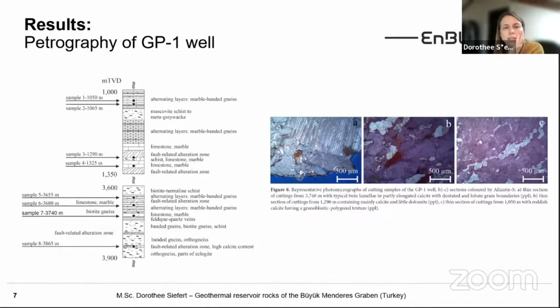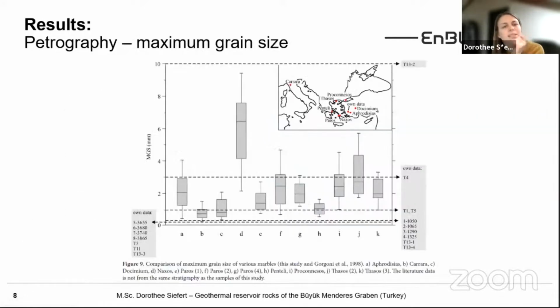And yeah, it contains a small amount, less than 5%, of quartz and mica. So about the maximum grain size we analyzed of the calcite and dolomite grains, they are in a quite small range, and one outlier is the Paleozoic outcrop sample T13-2. So here are our samples, and the box plots are the samples compared to various marbles in the region, but also in Carrara, for example. So the maximum grain size of the well samples appears to be small compared to the surface samples, but we can observe no systematic difference, and the cutting size is about 5 millimeters. So this may have influenced, of course, the maximum grain size determination of the well samples.